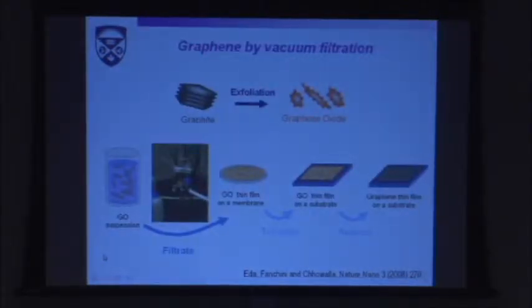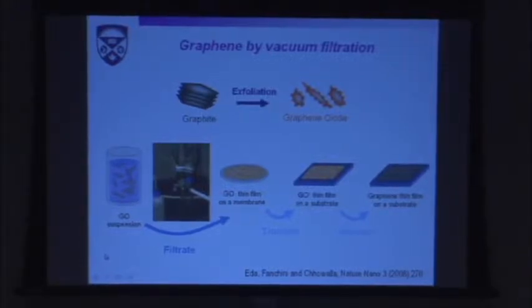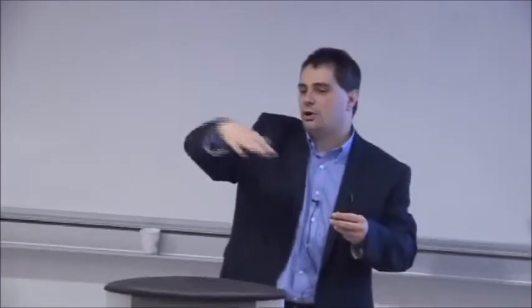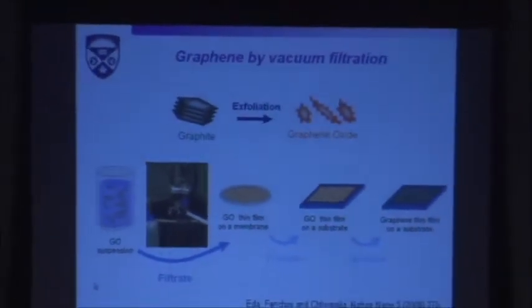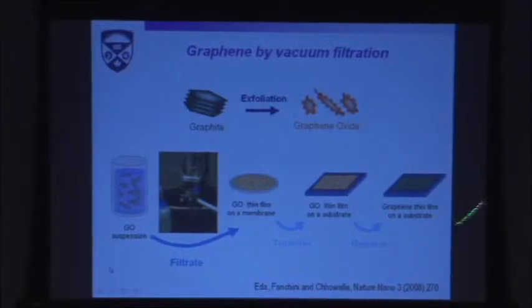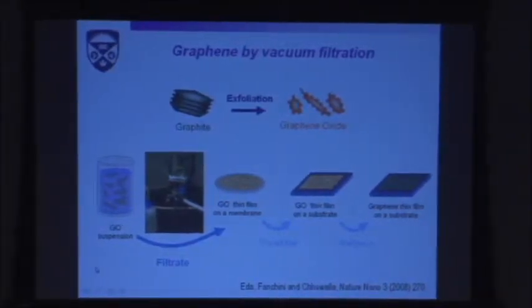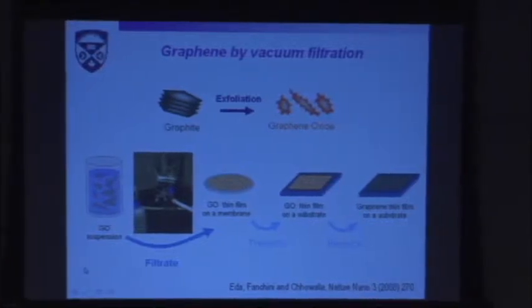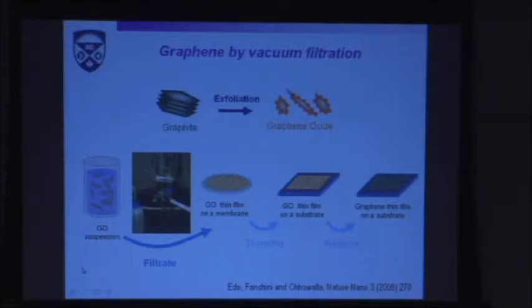Okay, you say, what is graphene oxide? This is the material that Brodie got in 1859 that was very thin. Is it just graphite? No, it wasn't just graphite. It's graphite decorated with oxide, carboxyl and hydroxyl groups, that keep it soluble in water, basically. So when you have your thin film on the substrate, it's time to get rid of these oxide groups, reducing the film. There are many ways to reduce these films, for instance by heating it up, or by appropriate reducers like hydrazines. They're pretty good at that. And you obtain a film that is nearly graphene, with very little impurities.